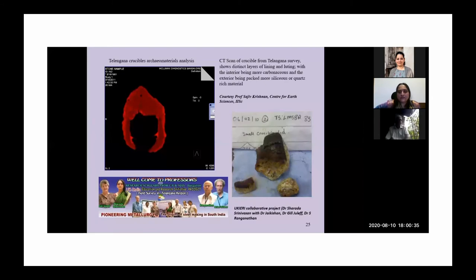And I think I didn't put in that dot map, but we also found that the outer layer was also quite rich in the element zirconium, in zircon. So they seem to have packed it with a lot of sands which contain zircon and things like that. And zircon is a useful material to have as a refractory because it tends to improve the refractory quality. And even today it's used in modern refractory materials and so on.